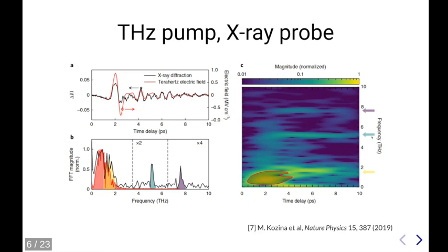And so you can see that it's generating in time this phonon, it's pumping a low energy mode, and this low energy mode is upconverting, is transferring energy to higher frequencies at 5 and 8 terahertz, which is very interesting and seems to tell us that this dynamics is very complex. So it's not just the ferroelectric mode that moves and drives the system out of equilibrium and into a ferroelectric phase, but it's actually interacting anharmonically with other modes in the system, and the real picture of what's going on